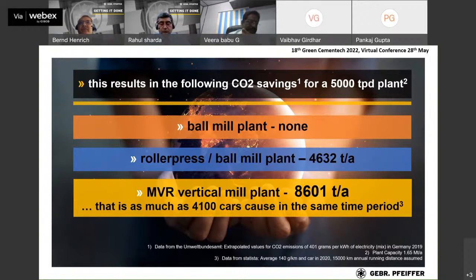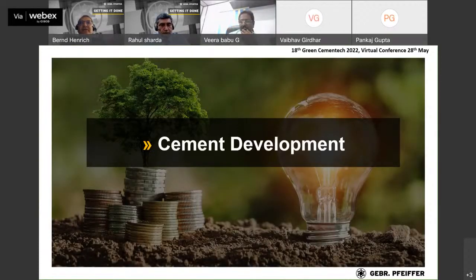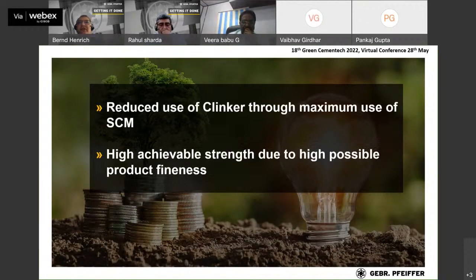So what kind of optimization can Gebrüder Pfeiffer do in this respect? For you, as a cement industry, we are first of all talking about the reduction of the clinker factor. Reduction of the clinker factor is a main step. We yesterday learned about situations using supplementary cementitious materials, so fly ash, pond ash as a wet fly ash which was stored somewhere, blast furnace slag. But in other parts of the world, except India, also limestone, natural pozzolana, and activated clay can be used as supplementary